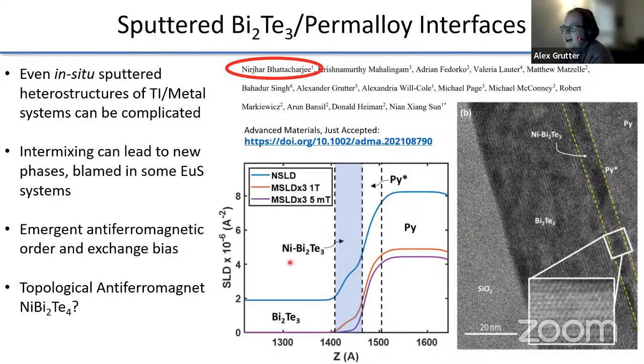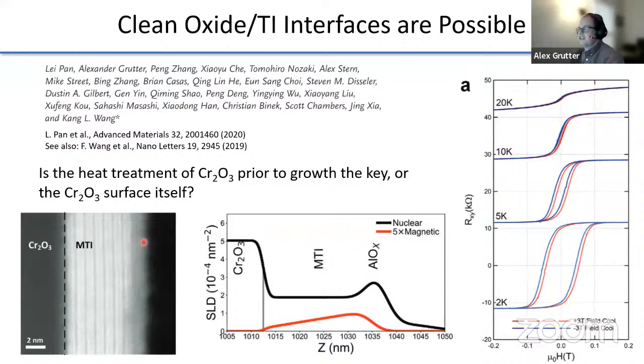And in fact, Nirjar has reason to believe that this intermixing leads to a completely new phase that may actually include the topological antiferromagnet nickel bismuth telluride, because they see the emergence of exchange bias in this system. And so that's very, very interesting. But of course, it is very much possible to get clean oxide topological insulator interfaces. This has been achieved numerous times, for example, in chromia next to topological insulator materials.